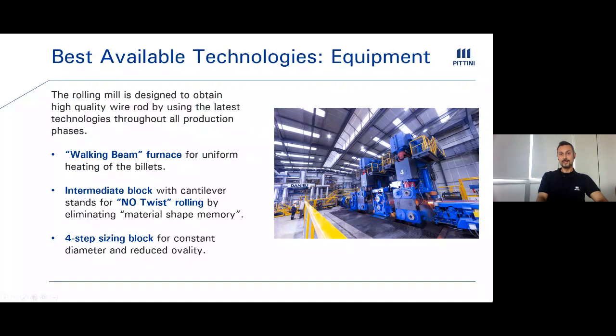Yes, concerning the best available technologies, we can underline two main aspects. The first is related to the equipment, and the second is related with the automation features of the mill. In relation with the equipment, earlier I mentioned the reheating furnace for the billet. That is a walking beam type furnace with two-side heating and selective temperature management for 9 zones. That's for uniform heating of the billets and to optimize the billet temperature and get a smooth and uniform rolling process. Passing through the selection of a no-twist rolling for the intermediate mill that allows us to avoid any quality issue that can be connected with the twisting of the material during rolling.